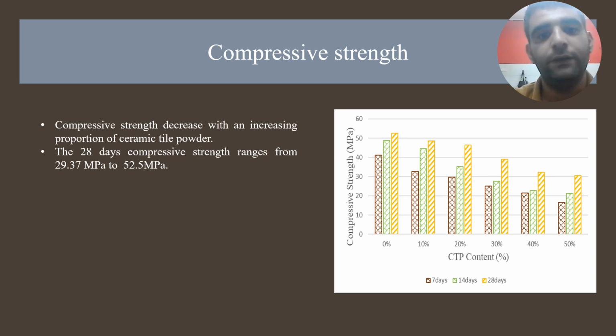The second test we have here is the compressive strength test. First of all, we can see in the figure the compressive strength of mortar with various percentages of ceramic tile powder content. We can see from the figure that compressive strength decreases with increasing proportion of ceramic tile powder. The 28 days compressive strength ranges from 29.37 megapascal to 52.5 megapascal, with the lowest compressive strength at 50% ceramic tile powder. We can see that at replacement of more than 20%, the compressive strength decreased significantly.